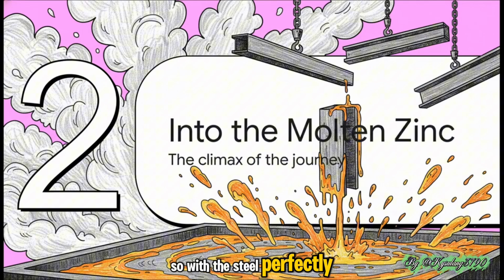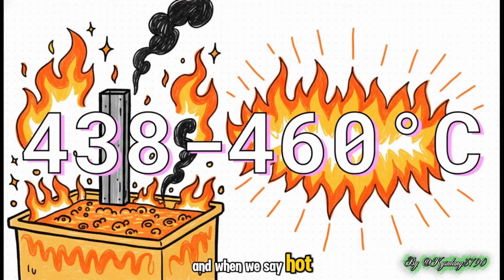So with the steel perfectly clean, it's time for the climax of the whole show, getting submerged into a massive vat of molten zinc, which is known as the galvanizing kettle. And when we say hot, we really, really mean it. The zinc is kept at a searing temperature, somewhere between 820 and 860 degrees Fahrenheit. This extreme heat is the engine that drives the whole chemical reaction between the zinc and the steel.